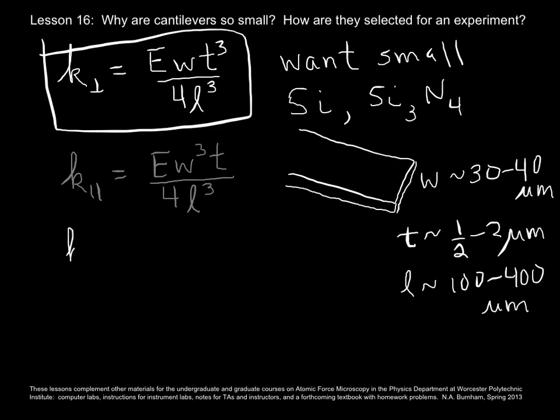And then, what about the spring constant when you apply a force to the tip that, instead of being perpendicular to the sample surface, is parallel to the sample surface and perpendicular to the long axis of the cantilever? This would be what happens in lateral force microscopy. Well, you get the shear modulus times the width times the thickness cubed divided by 3 times the length times the height of that tip squared. And I'm going to use eta, because I use h for other things. And that can range from 5 to 20 microns.